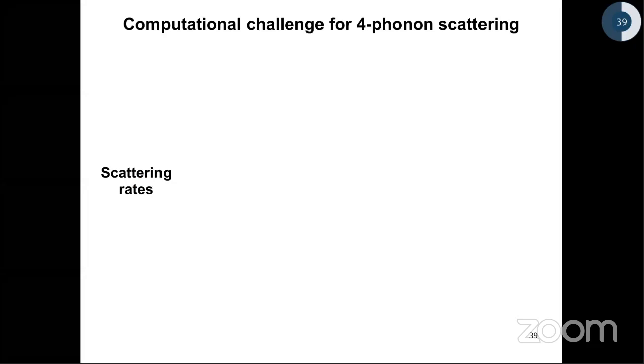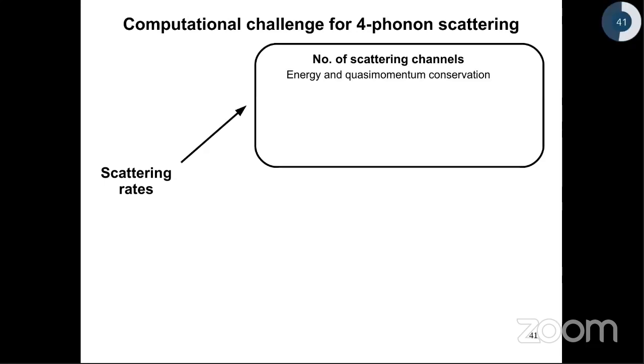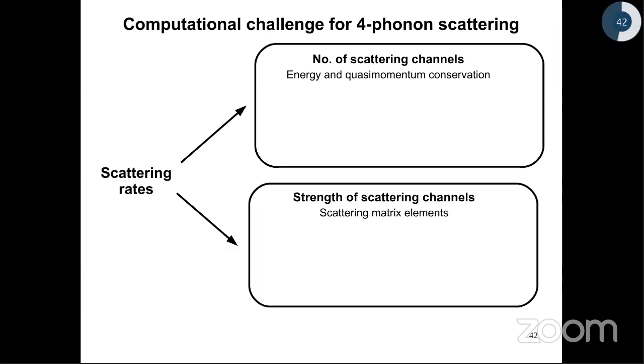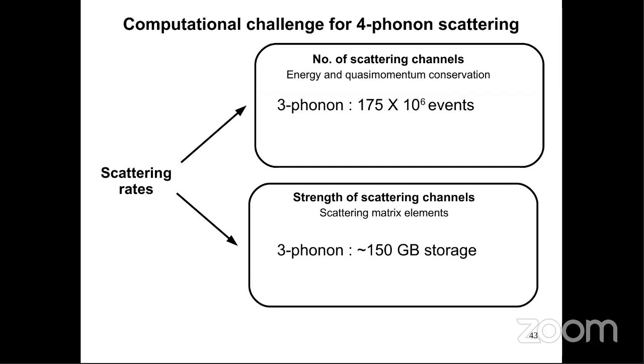So before I show you some results, let me just give you a flavor of how challenging this computational work is to calculate 4-phonon scattering. So the problem boils down to actually just calculating the scattering rates. If you have the scattering rates including 4-phonon processes, you can eventually get the thermal conductivity with very little work. So this process can typically be broken down into 2 sections. The first one is to count the number of scattering channels that are allowed according to the energy and quasi-momentum conservation constraints. And once we have this list of allowed scattering channels, we can calculate the strength of each and every channel. This is where the anharmonicity of the crystal comes in, which describes the strength of each and every channel. And putting these two together, we can calculate the scattering rates through Fermi's golden rule. So if you look at a typical conventional approach calculation, that is calculation involving 3 phonons for a reasonable grid, I think these numbers are for a 21 cube grid in the Brillouin zone.